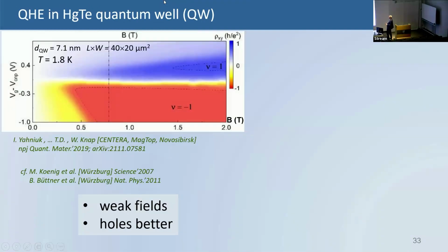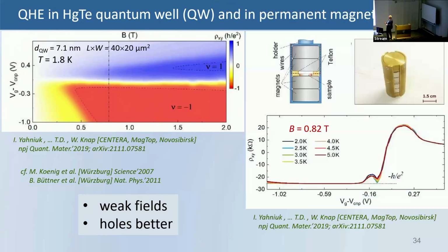And what the experiment tells is that you have here the quantum Hall effect, and you see that the quantum Hall effect for holes extends to much lower magnetic field. Here's the magnetic field. Here's the gate voltage by which you can change carrier density. And the color code gives you the Hall resistance. And you see this Hall resistance at much lower magnetic field for holes than for electrons, contrary to other materials.